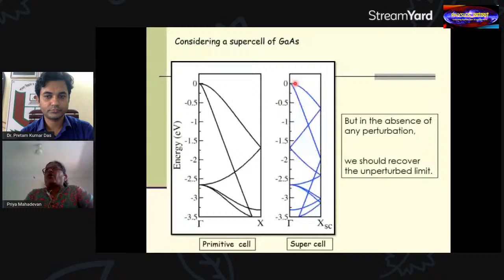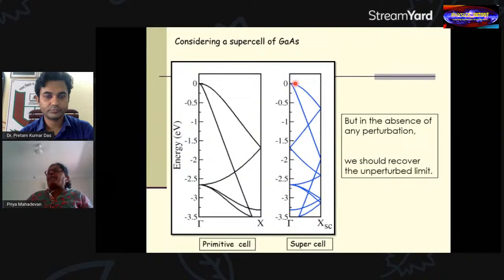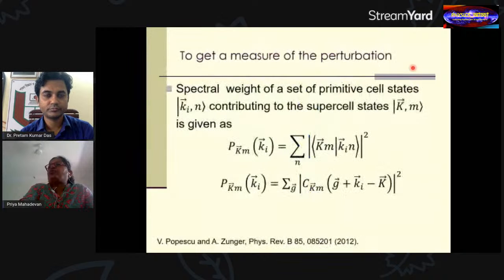But that's not correct, because I was constructing a supercell and there is no perturbation over here. My unit cell dimensions have become much, much larger, so my reciprocal space has shrunk, and therefore I come to a case where the band dispersion is not correct. I should recover the unperturbed limit of the band structure, because when I'm just constructing a supercell, I have no perturbation at all in the system.